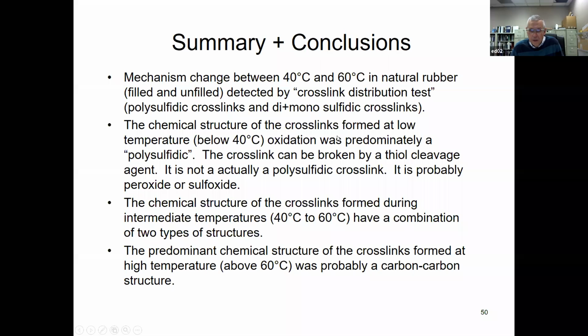The chemical structure of the crosslinks formed at low temperature, below 40 degrees C, was predominantly polysulfidic. The crosslink can be broken by a thiol cleavage agent. This is not actually a polysulfidic crosslink. It is probably peroxide or sulfoxide.